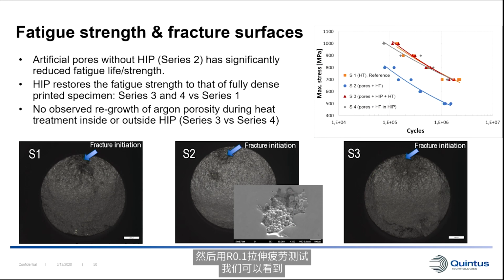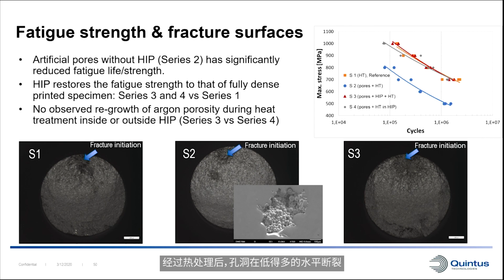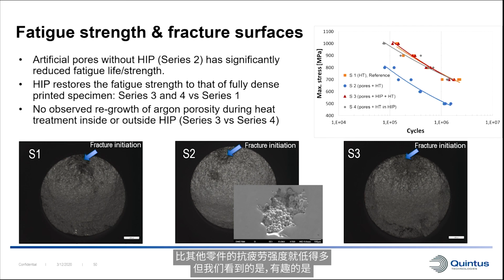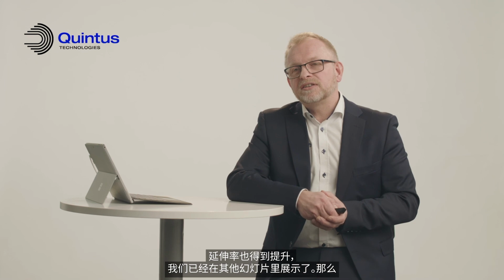And what we can see here is that the Series 2, which is the printed material with the heat treatment and the pores, fractured at much lower level, has a lower fatigue resistance than the other parts. But what we could see is, and interestingly, the material that was printed with very large pores, actually, in this case, achieved extremely good fatigue resistance after the high-pressure heat treatment or the HIP and heat treatment cycles. But, of course, with the improved elongation results, which we already showed in the other slides.